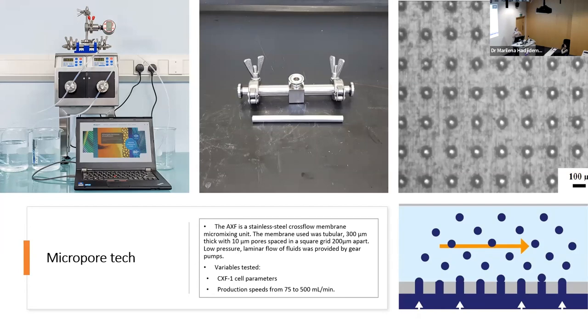We are also beginning to look at micropore technology as an alternative. All the cartridges are moving to single use, which has advantages for clean room validation. However, during the pandemic, the supply chain fell apart and even pipette tips were unavailable — so access to consumables becomes a production risk. The micropore technology uses a tube with an insert, flowing ethanol through to mix with the aqueous phase, achieving nano-precipitation. Most of the data I'm presenting today is based on PNI technology, but there are many options, balancing single-use convenience versus reusable stainless steel with cleaning validation between preps.